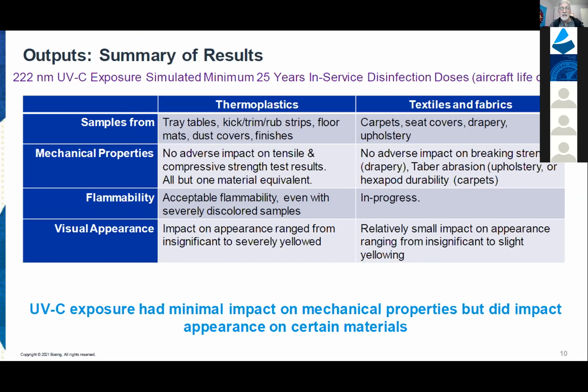And what was interesting is we did not see anything. We only had one sample material. It was a polyurethane, and its compressive strength, I think, dropped a little bit. It was statistically significant, but well above the requirement. Everything else was basically equivalent. We did not see any impact whatsoever. That's mechanical.